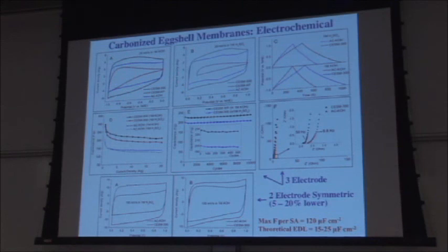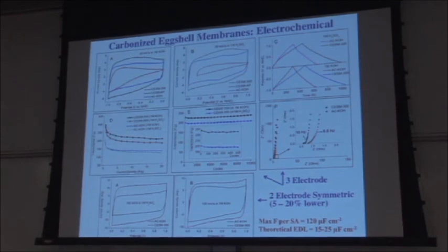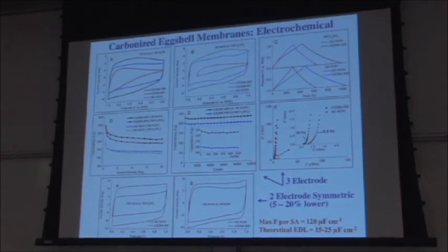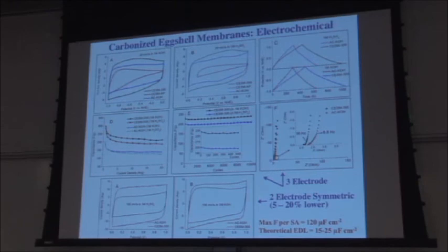And people don't actually quite know what they are, but they're there, both on the reduction and the oxidation. We tested both in KOH and sulfuric acid. It worked quite well. If you look at the charge-discharge curve, very low IR drop, asymmetric because of the Faradaic reactions. If you look at the specific capacitance, this is a carbon. There's no oxide on here. It's just a low surface area carbon, 200 meters squared per gram.